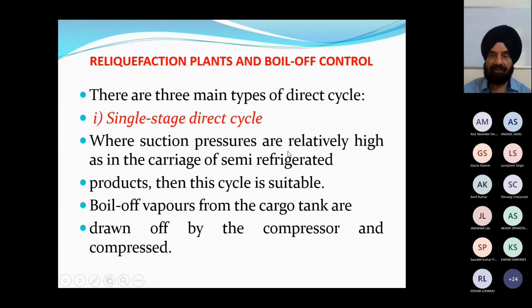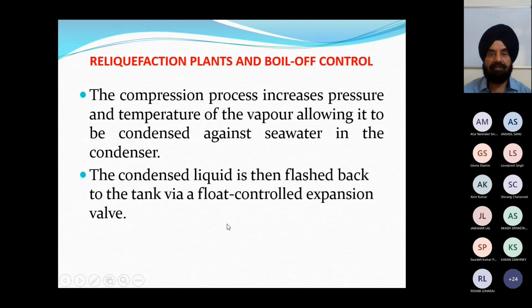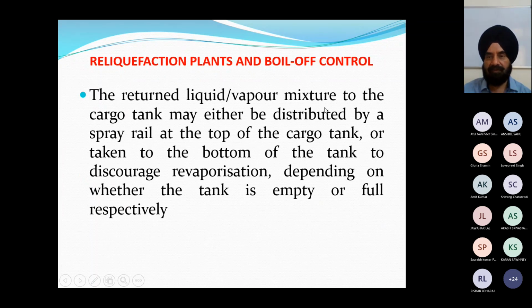Single stage direct cycle is used where suction pressures are relatively high, as in carriage of semi-refrigerated products. Then this cycle is suitable. Boil off vapors from the cargo tanks are drawn off by the compressor and compressed, and the compression process increases the pressure and temperature of the vapor, allowing it to be condensed against the seawater cooled condenser. This condensed liquid is then flashed back to the tank via a float controlled expansion valve. The returned liquid or vapor mixture may be slightly, not completely, converted to liquid. This mixture goes to the cargo tank, either distributed by a spray rail at the top of the cargo tank or taken to the bottom of the tank to discourage more revaporization, depending on whether the tank is empty or full respectively. Sometimes we do spray to vaporize to cool the tank, but here it is basically to reduce the vapor pressure, to convert these vapors back into liquid.